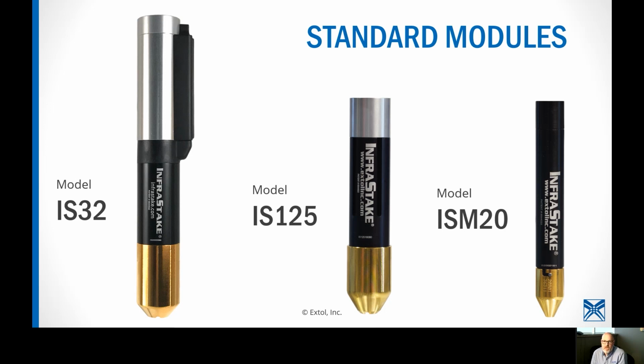Yeah. I want to talk about that for a second. Short answer is yes, but let's dive into that a little bit. I realize you guys are looking at a different slide now, the different models that are available. But if InfraStake is in process, so in other words, we've set the machine up, we've dialed it in, and it's doing what it's expected to do, it creates very little off-gassing. However, like any other technology, you can change the process parameters, get it out of tune, if you will, and then it will create higher levels of off-gassing, which can result in soot or a layer. And then, yes, they will need to be cleaned.